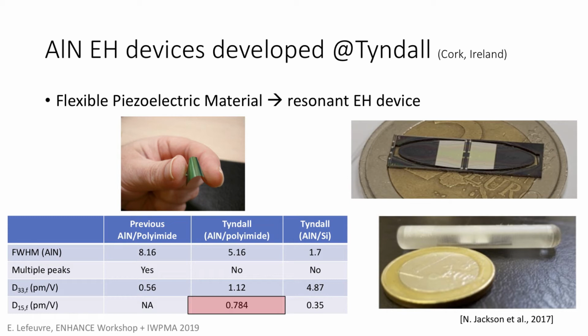But if we look at the figures on silicon, the D33 is much better. So they decided to keep this kind of substrate for the device, which is here. So you have the device that they developed. It's composed of 2 cantilevers. This is the inertial mass here and there. So it was not based on the microbellows for the actuation. It was based on the motion of the capsule. And you have here a view of the device inside of a transparent capsule. It's not titanium, of course. It's not metal, but it was just to show that it fits into the good dimensions. So it worked, and we had something to show to the European Commission at the end of the project.